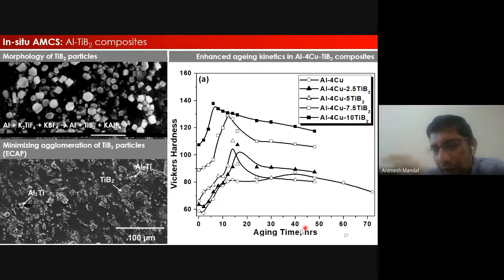That means from 40 hours in an alloy, by adding reinforcement, you have brought down the peak hardness time of your composite. So what it's doing is enhancing what we call the aging kinetics. Having a composite is beneficial also for accelerating the aging kinetics, meaning the precipitation of this Al2Cu, which is present in this alloy, can occur at a much lower time, and that's a significant improvement. For example, you can see here from 40 hours you have reduced all the way to 8 hours. That has a very industrial implication as well, because you're going to reduce the heat treatment time.